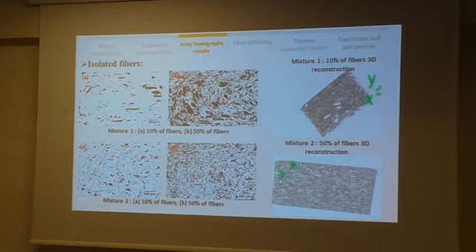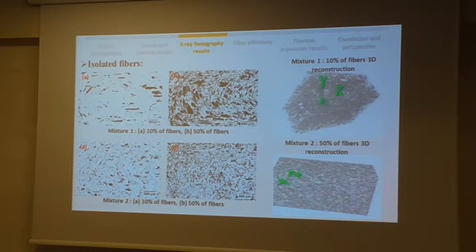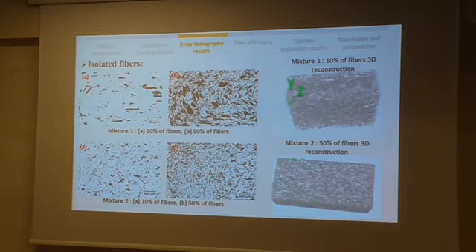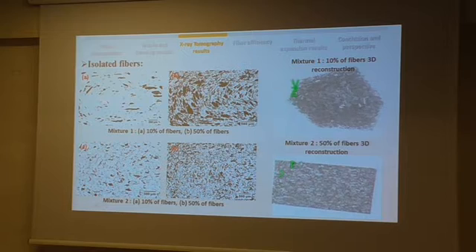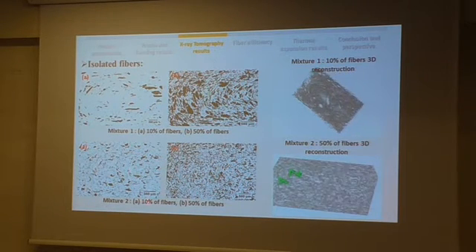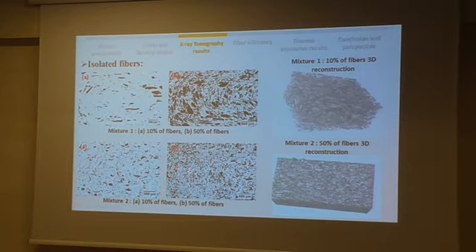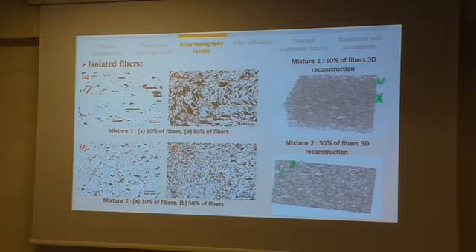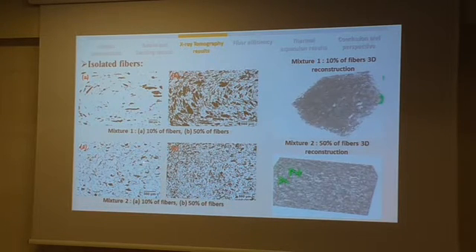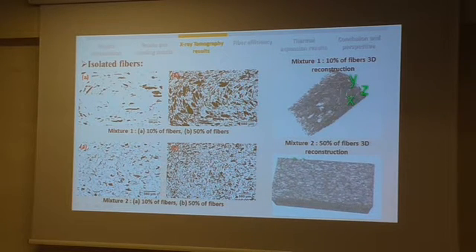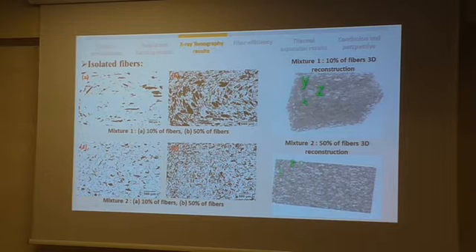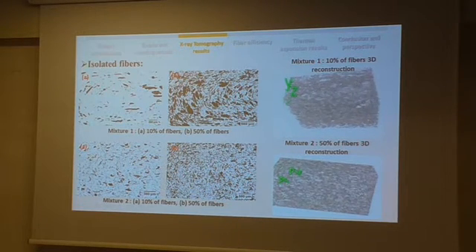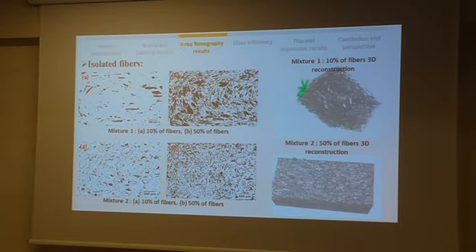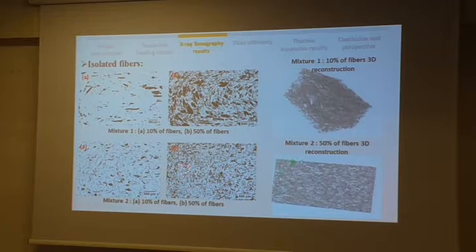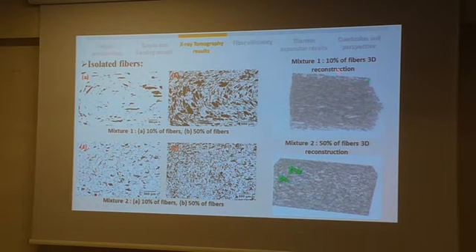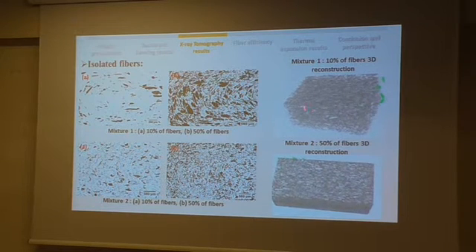So, here is an example of fiber distribution of mixture 1 and 2 with 10% in image A and 50% in image B for mixture 1, and 10% and 50% for mixture 2. And we can notice here that for mixture 2, the one with the 200 microns particle, the distribution is more homogeneous in the volume. And that can be explained by the lower viscosity of this mixture in the injection phase. And we were able also to reconstruct a 3D model of the fiber distribution for this mixture.